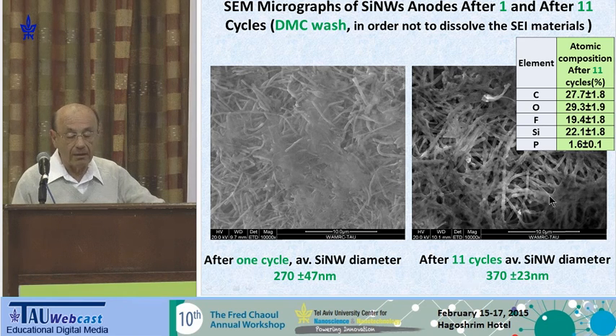Now here you see the composition of the film deposited on the nanowires. We have fluoride and phosphorus atoms coming from the reduction of the salt, which is lithium hexafluorophosphate, and oxygen and carbon coming from reduction of the solvent. As I said, we have lithium carbonate, semicarbonate, and ketones, or whatever.